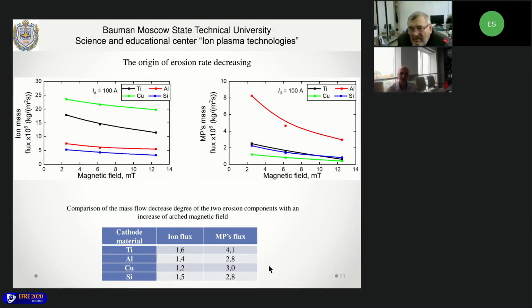from the magnetic field. In this picture, you can compare the two pictures of ion mass flux and macroparticles mass flux reduction from the magnetic field. And in this table, I placed the numbers that may help you compare these pictures. As you can see, the ion mass flux reduction is not so drastic as in the macroparticles flux. So we can conclude that the erosion rate decrease is mainly from the macroparticles flux decreasing.